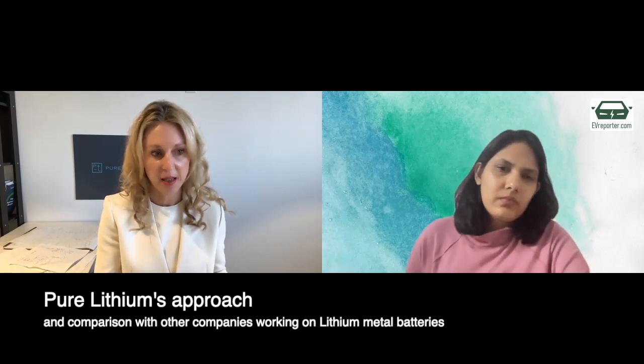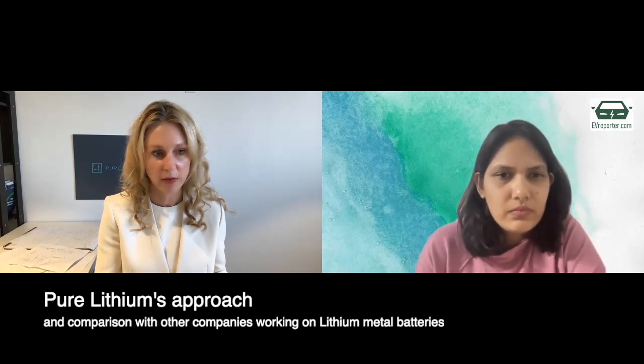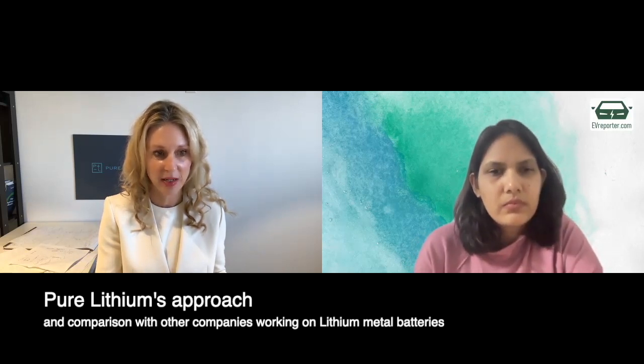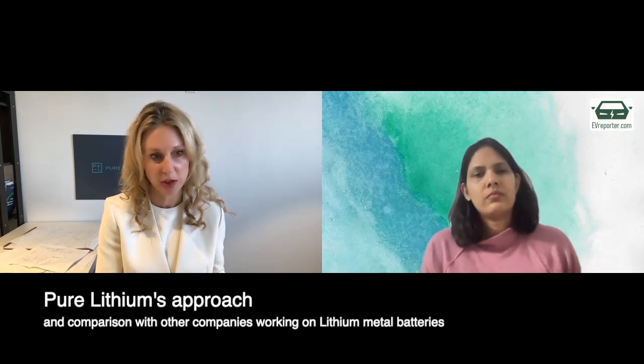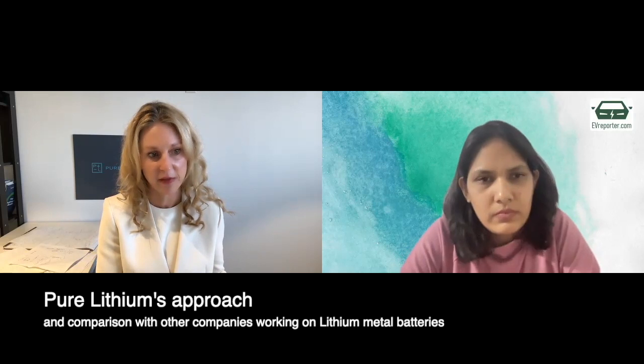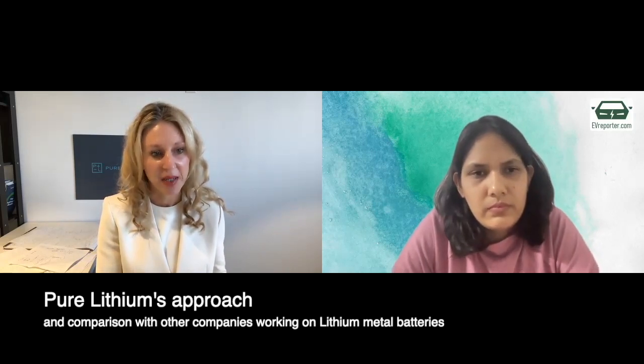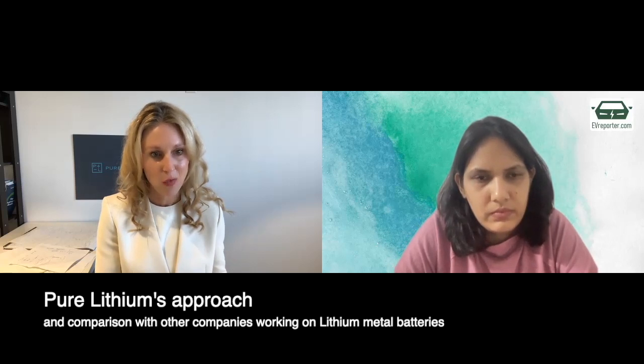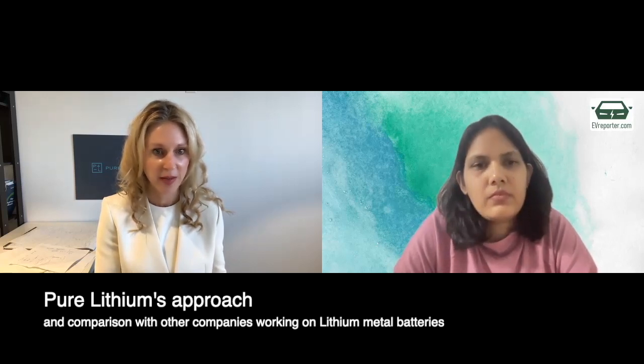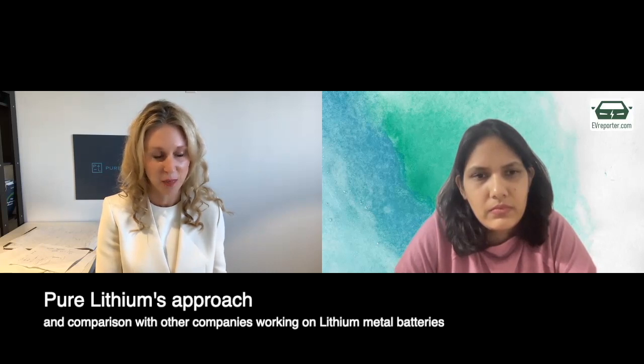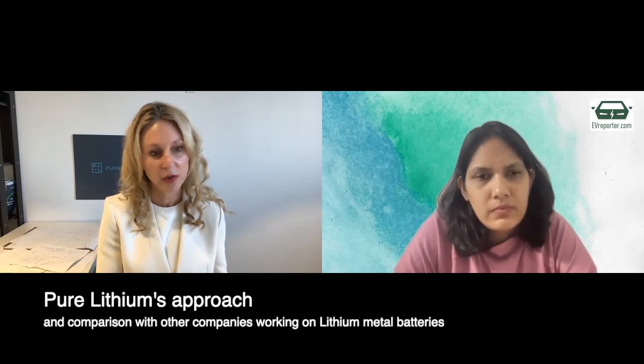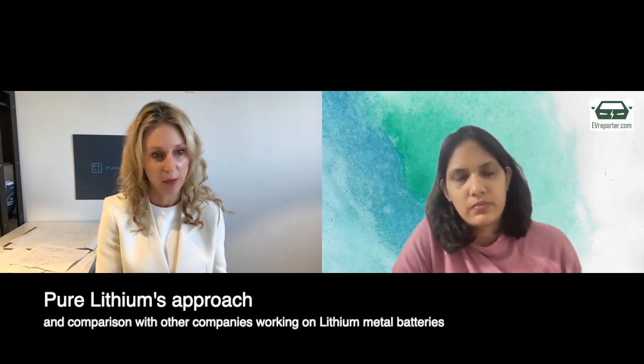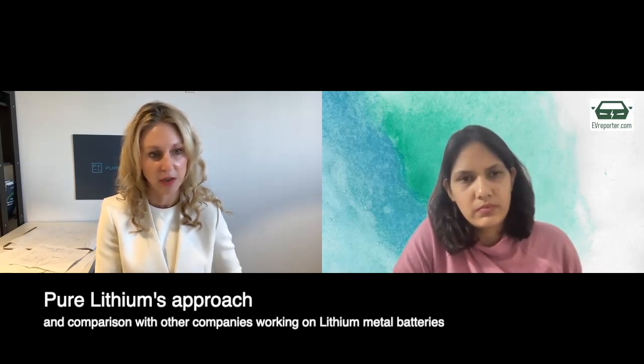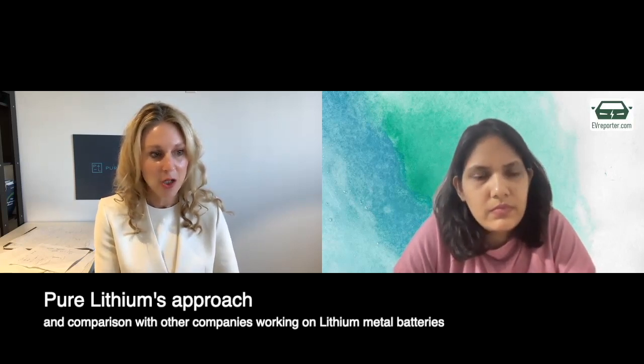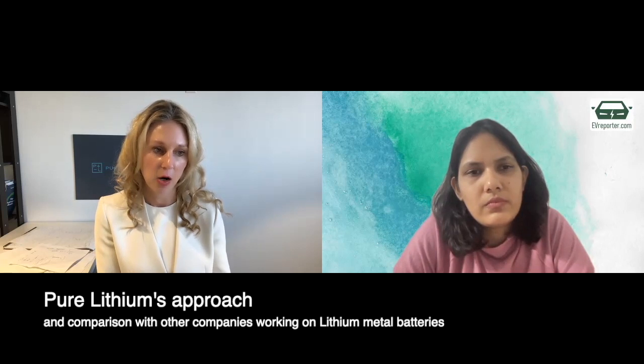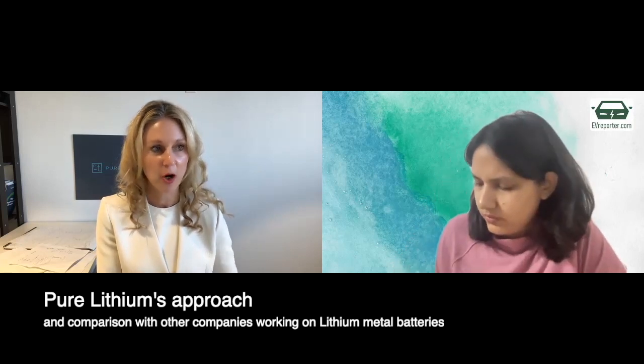But the big win for us is that we invented a way to use a myriad of different feedstocks. So instead of lithium chloride that I mentioned at the beginning of our conversation, that's only 3% of the market and is very expensive, we can use a lithium sulfate solution that people are working on making right in the United States. We can use off-spec lithium carbonate, and a lot of lithium carbonate gets thrown away if it doesn't meet super high spec. So we can also use recycled lithium ion batteries. We've done a lot of that work in our lab using some novel molten salt electrolytes that Don Sadoway has invented. So the other thing we do differently, besides making our own anode, we also make our own polymer.